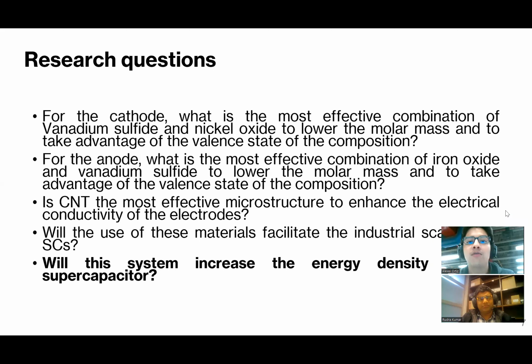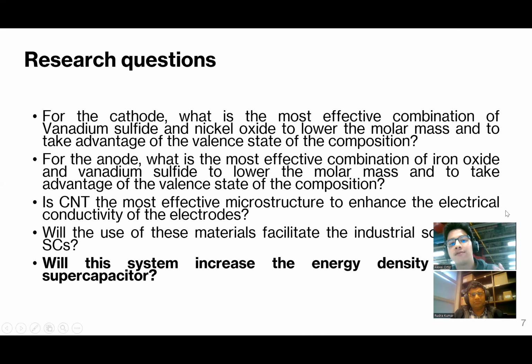Well, for the cathode, what is the most effective combination of vanadium sulfide and nickel oxide to lower the molar mass and to take advantage of the valence state of the composition, given that the materials have multiple valence states, multiple electron states in the last layer?